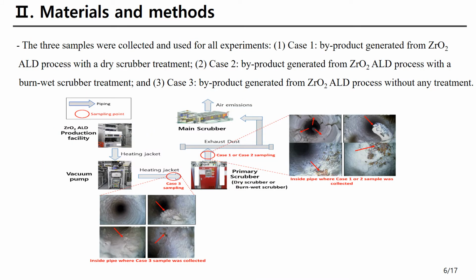The 3 samples were collected and used for all experiments. Case 1, byproducts generated from zirconium oxide ALD process with a dry scrubber treatment. Case 2, byproduct generated from zirconium oxide ALD process with a burn wet scrubber treatment. And third, byproduct generated from zirconium oxide ALD process without any treatment.